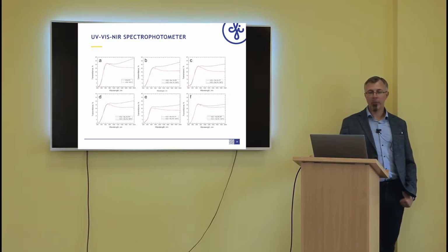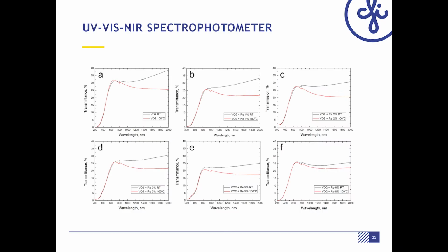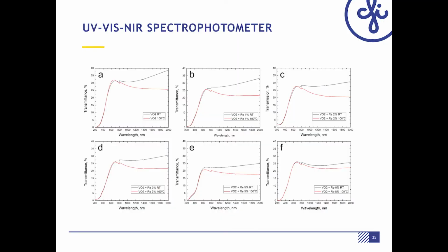To see how effectively works vanadium dioxide doped with rhenium, we also studied transmission spectra of vanadium dioxide coating at room temperature and at elevated temperature, 100 degrees in this case. And you can see that with increasing amount of rhenium in film, thermochromic performance decreases.